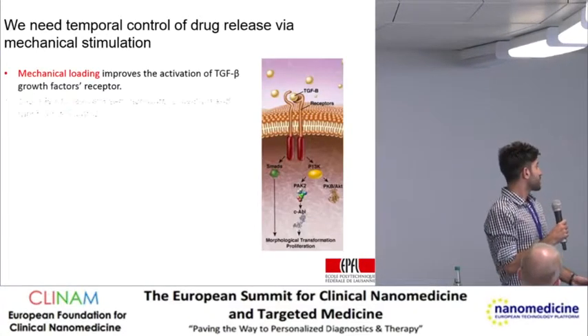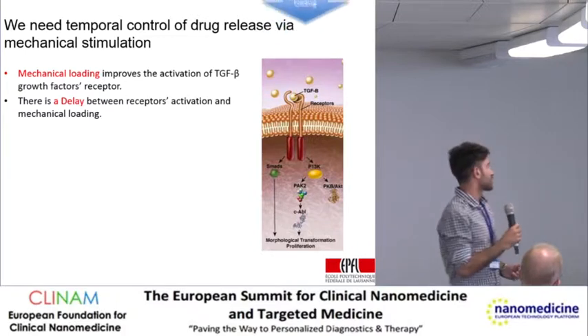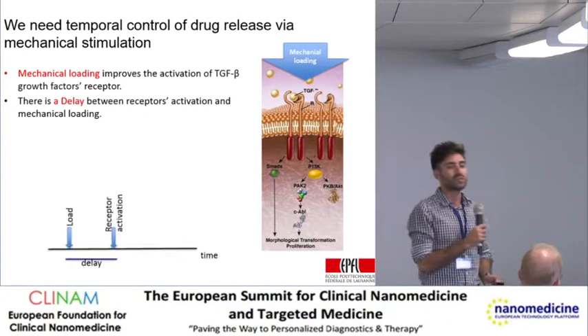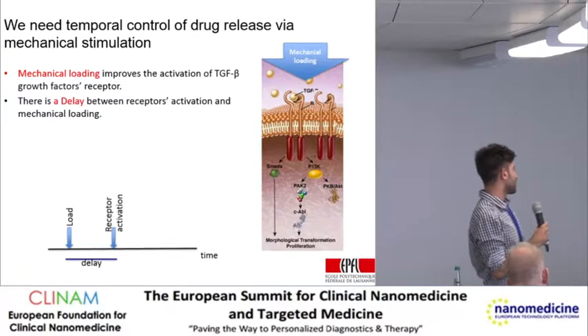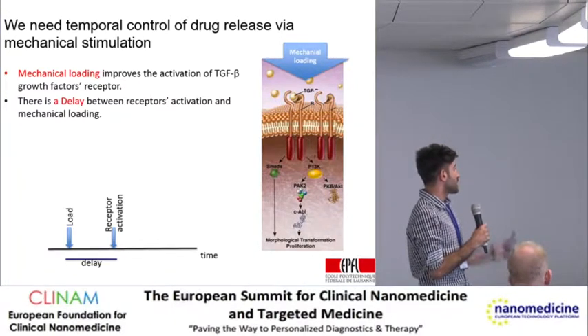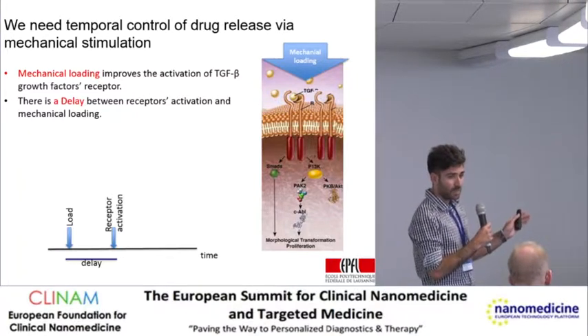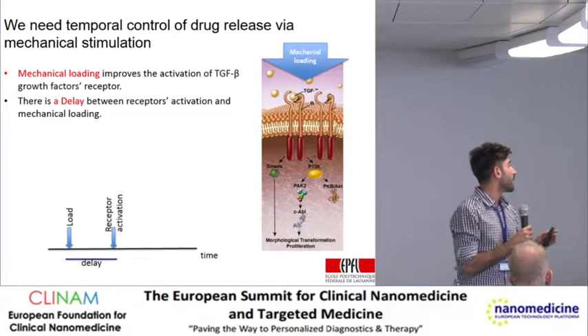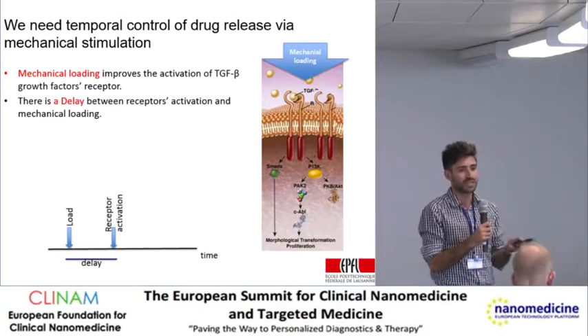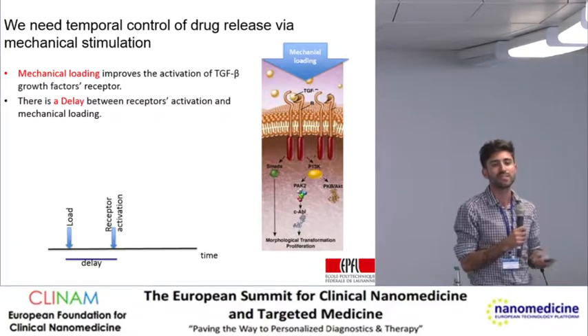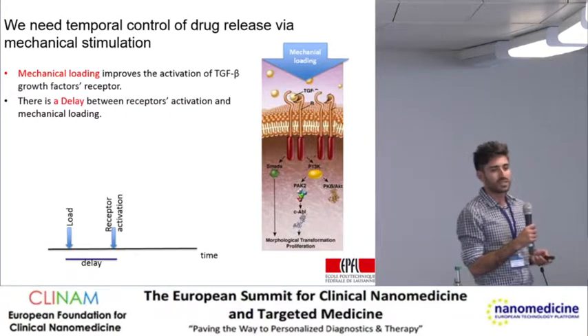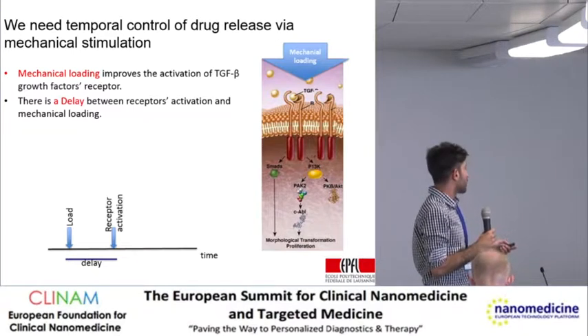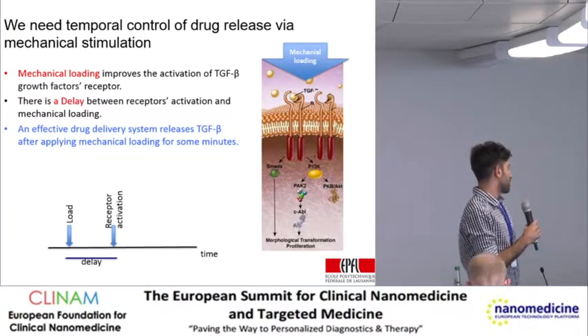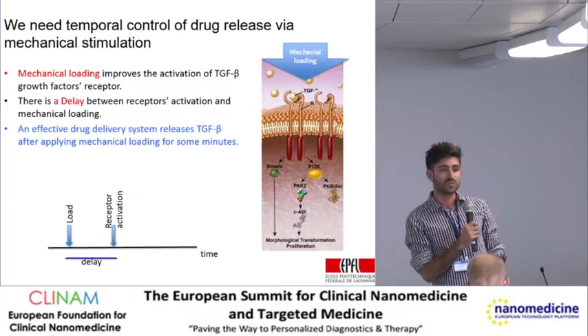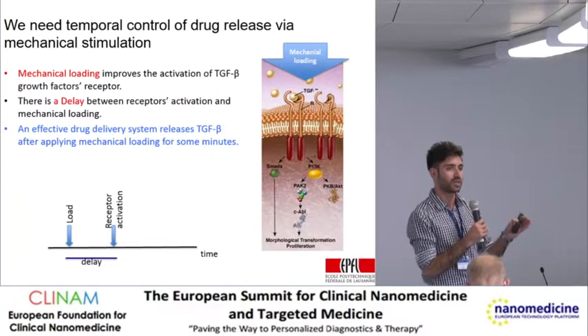Mechanical loading improves the activation of TGF-beta growth factor. That means that when you have mechanical load, you have more receptors upregulated. This has been shown in literature. And interestingly, there is a delay between when you apply mechanical load and when these receptors are upregulated, because there is a cascade of events. It has been shown it takes about 20 minutes to half an hour to respond to this mechanical load. So to have an efficient drug delivery system, it's good to have one that controls the release with mechanical load and provides such a delay between applying the load and release of the drug.